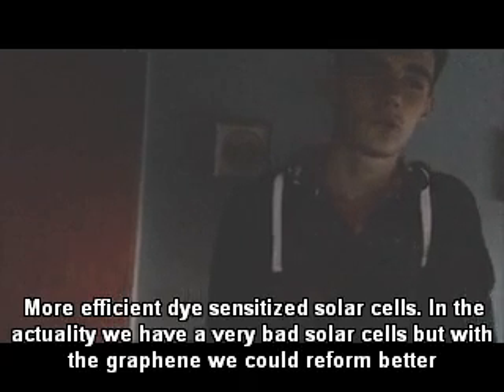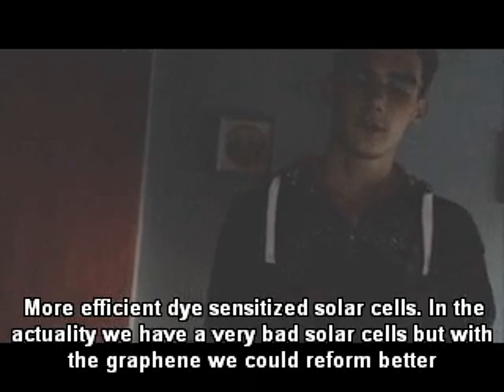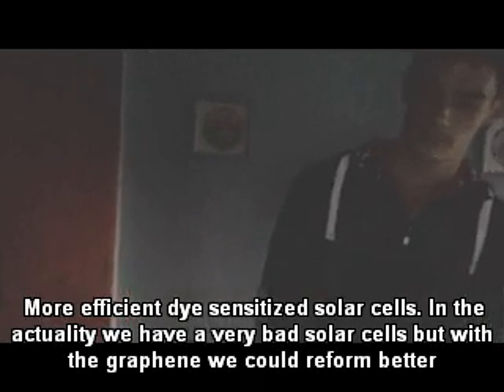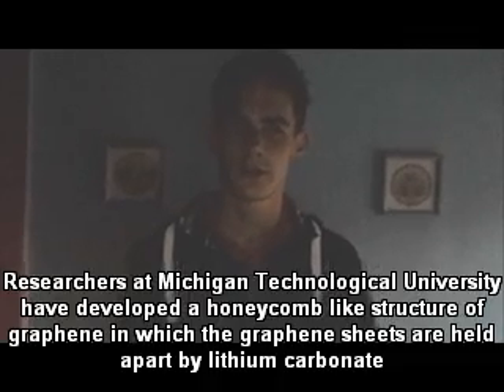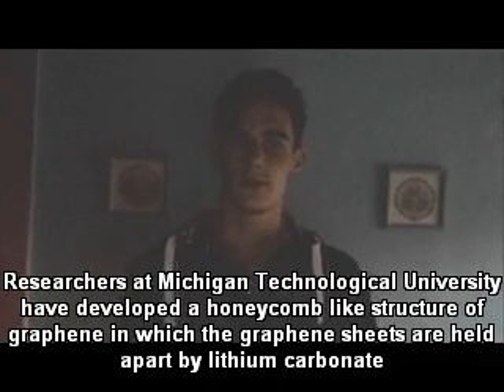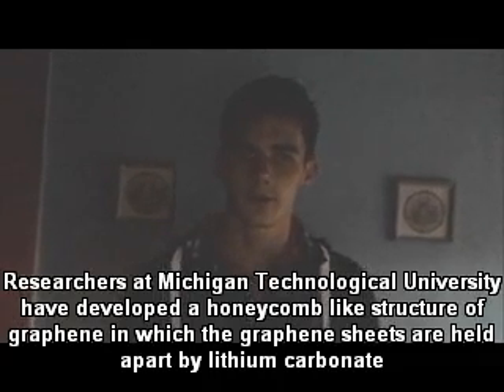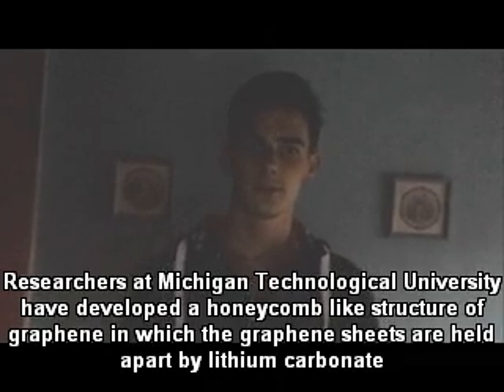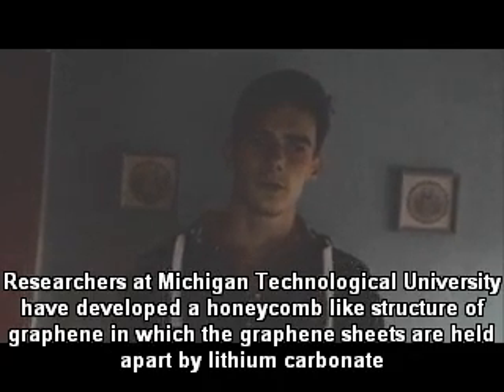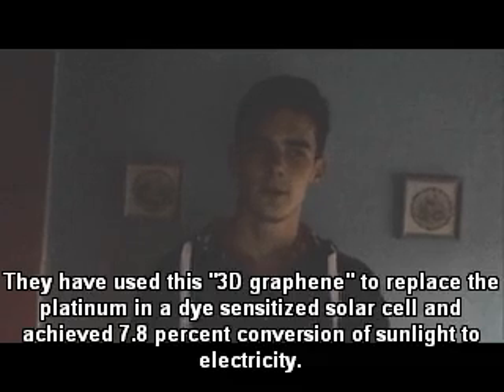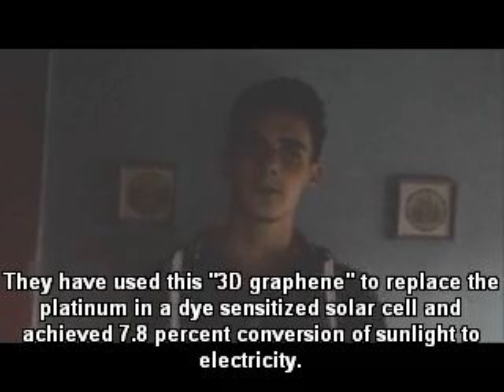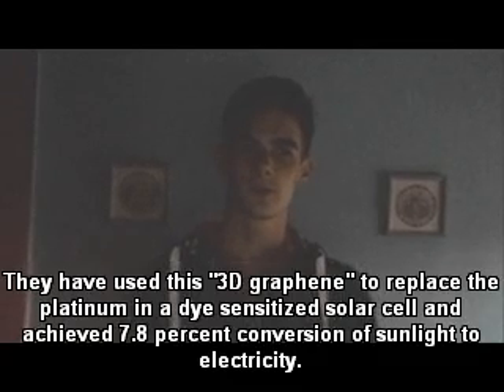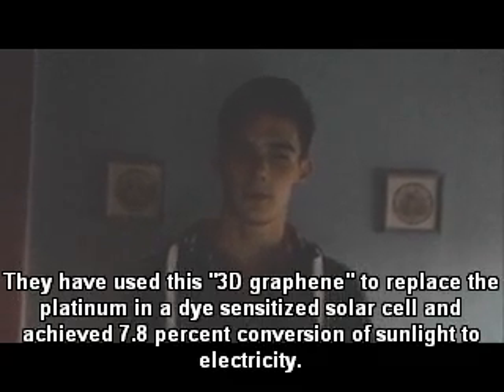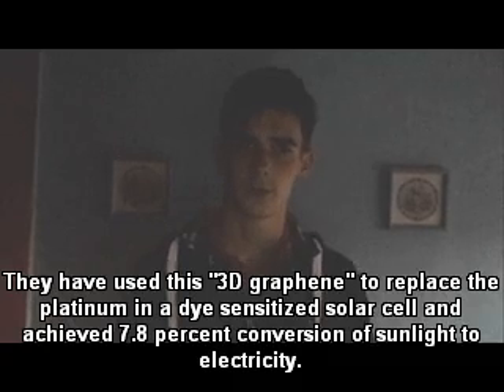More efficient dye-sensitized solar cells. Currently, we have very poor solar cells, but with graphene they could perform better. Researchers at Michigan Technological University have developed a honeycomb-like structure of graphene, in which the graphene sheets are held apart by lithium carbonate. They have used this 3D graphene to replace the platinum in a dye-sensitized solar cell and achieved 7.8% conversion of sunlight to electricity.